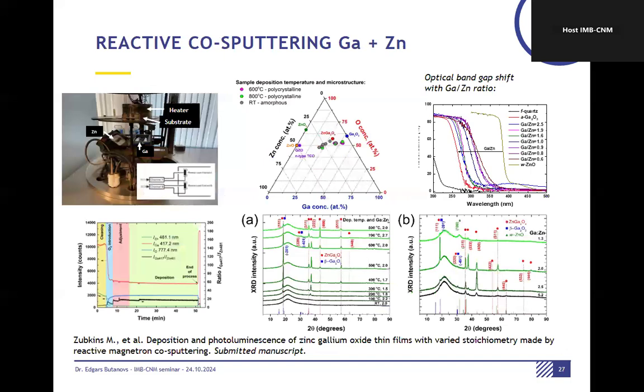What we also explored is alloying with zinc. So we have a gallium target here, and we also use a zinc target, and we could obtain different types of material: first of all, zinc alloyed gallium oxide, or a solid solution of zinc oxide alloyed with gallium, and as well, in specific conditions, we could obtain a very nice spinel phase, zinc gallate.